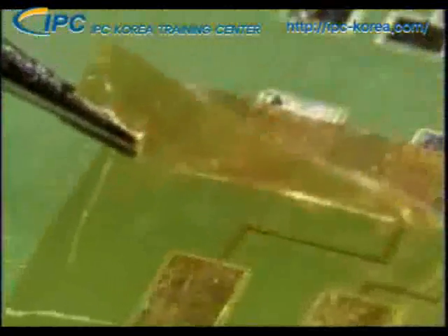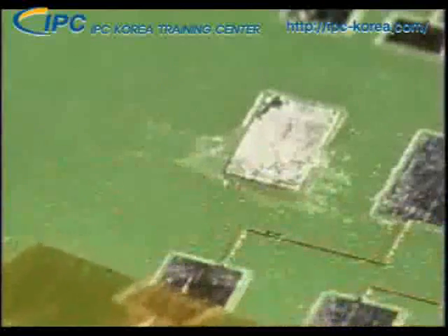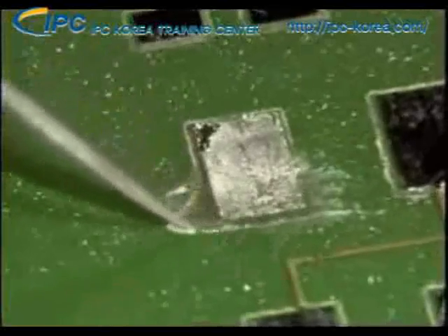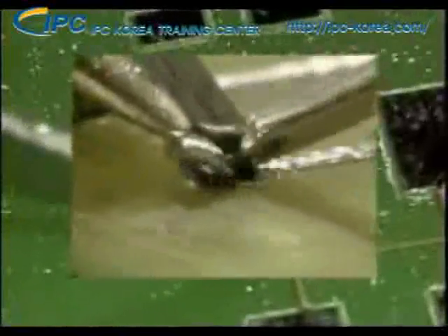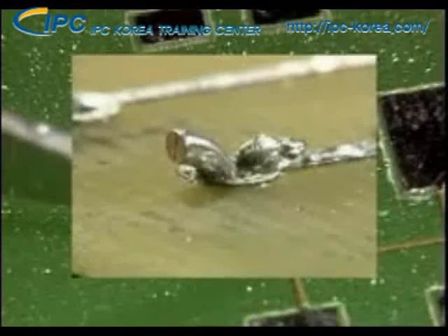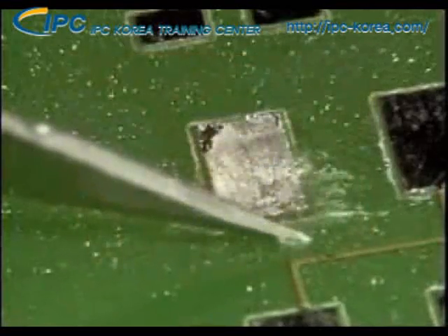Then slowly and gently remove the tape that was used to cover the land. If some of the adhesive material has oozed out a little bit from the edge, use a small utility knife blade to clean it away. Carefully trim along the edge with the tip of the knife, then gently scrape the excess adhesive out of the way. If dry film adhesive spreads on top of the land during the reflow curing process, later on it can interfere with the formation of a good solder fillet. Finally, clean the area and blot dry.